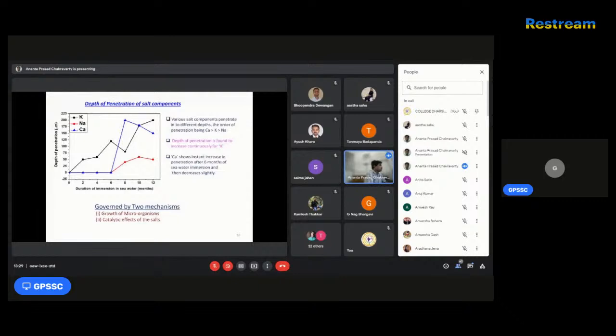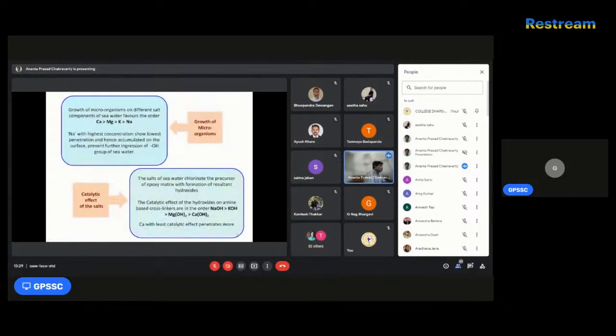We have mapped that with respect to the period of seawater immersion, the salts are penetrated up to a vast extent, and then we have plotted the depth of penetration of the salts with respect to seawater. These are analyzed typically due to the growth of microorganisms. These are locking some of the salts, and those are used as nutrients for their bacterial growth and catalytic effects of the salts. So from those EDS mappings, I could realize that calcium is penetrating more than magnesium, then potassium, then sodium. This is the trend of the penetration of the salts.